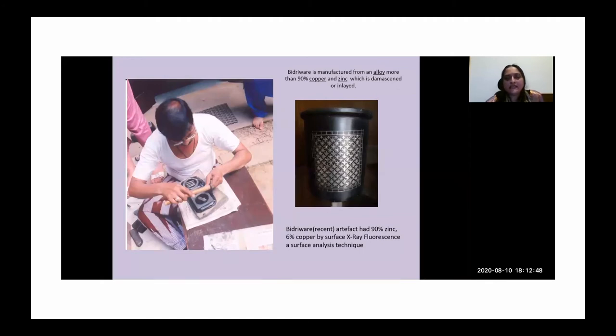And of course, amongst the techniques that we often use to analyze artifacts, one of the useful ones is XRF. And XRF works for artifacts like this, which may not have corroded too much. It's not that helpful when we come to copper artifacts or iron and so on, which can have a lot of corrosion over a long period of time. But some of these kinds of artifacts, like more recent Bidri ware, which hasn't corroded too much, it's quite useful. And here, this was some analysis that we had made, which shows that it was 90% zinc alloy with about 6% copper.